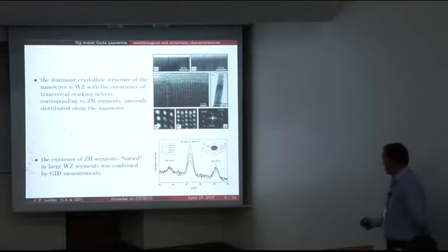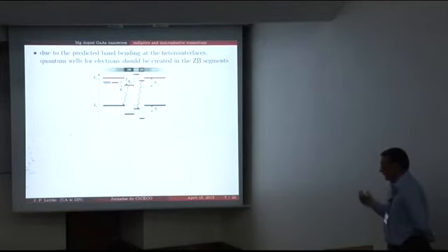The contribution from the wurtzite must come just from the gallium arsenide nanowires. Why? Because in the epitaxial layer, as far as we know, until now, no one was able to grow wurtzite gallium arsenide. So these results confirm these results from there.